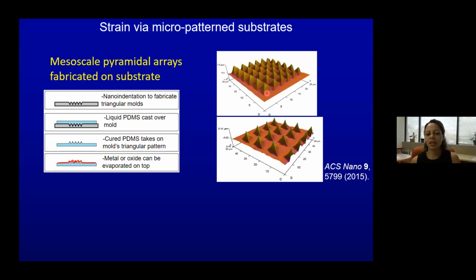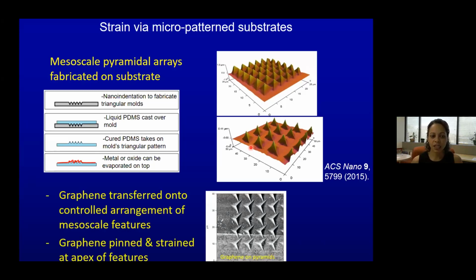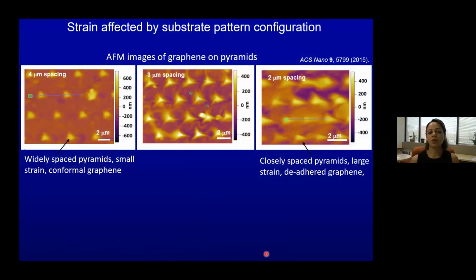And so what we ended up with are these beautiful pyramidal type features that are spaced by a couple microns, and we could control the configuration of these and see how the configuration of features affected the adhesion and the strain in graphene. Okay, so we transferred graphene onto this arrangement of mesoscale features and found that the graphene indeed pinned and strained at the top of the features. Well, how do we know that? One thing we did was atomic force microscopy.